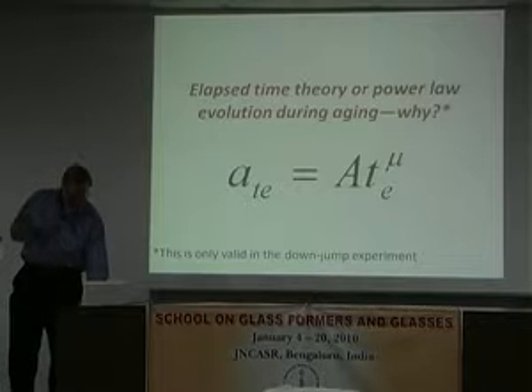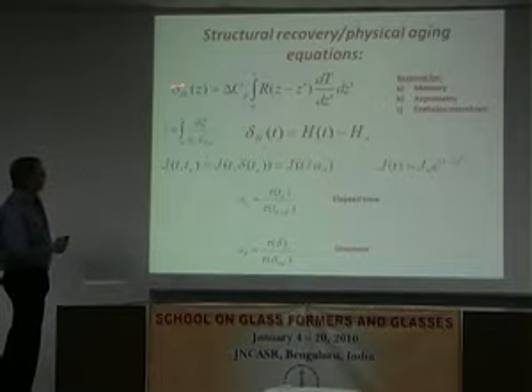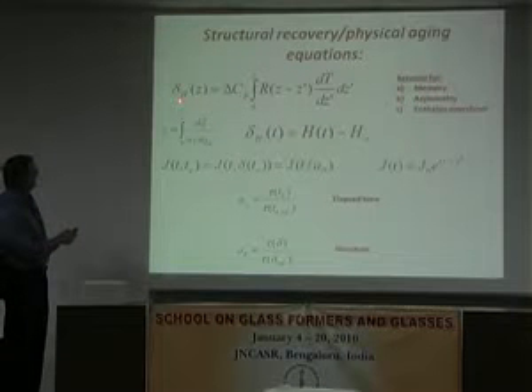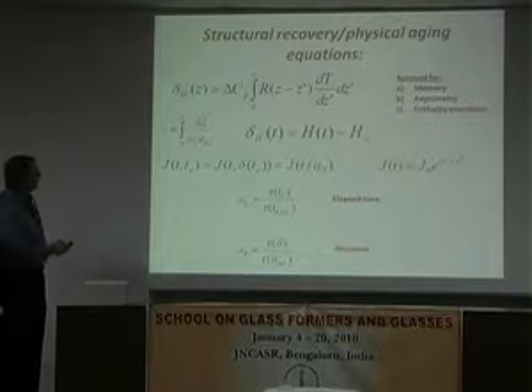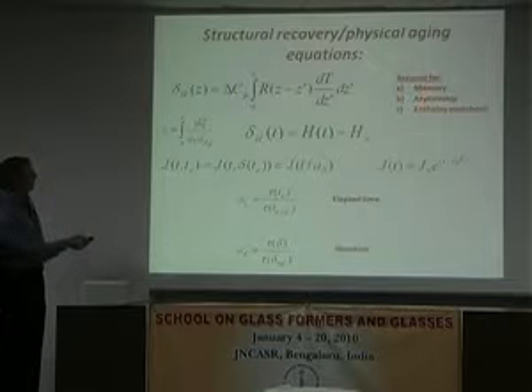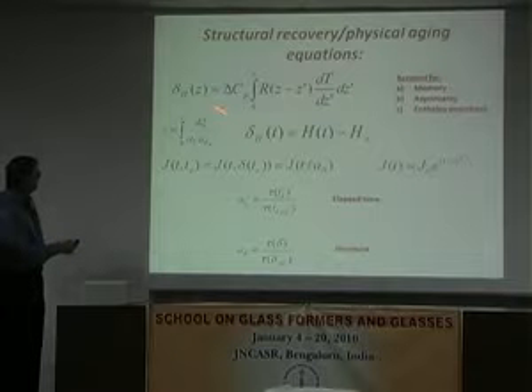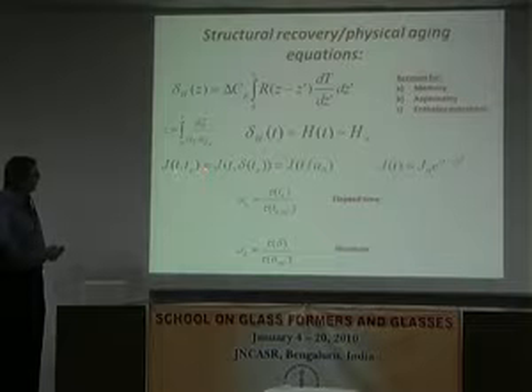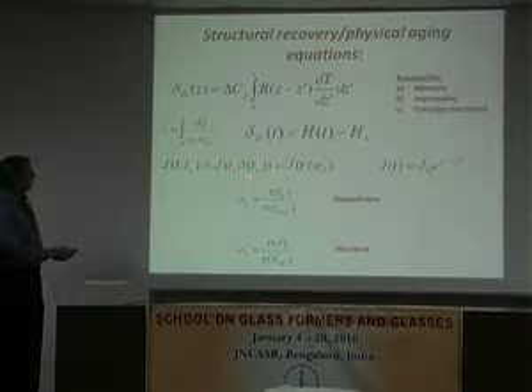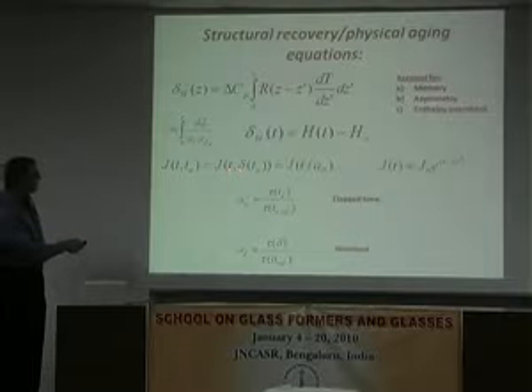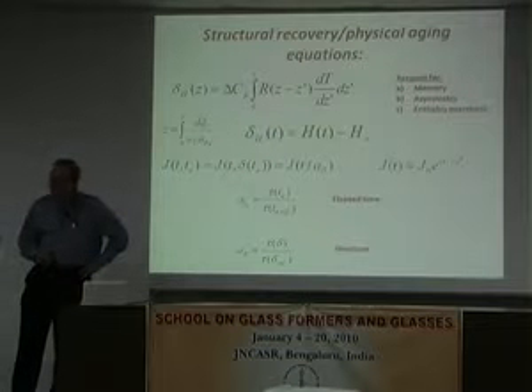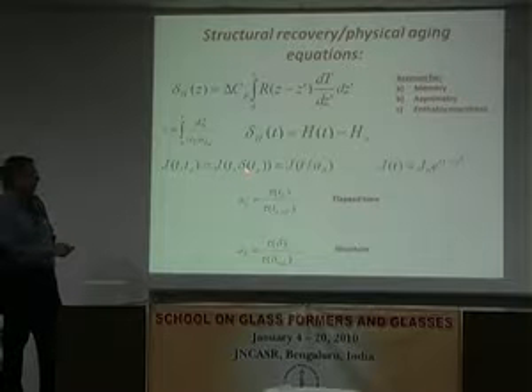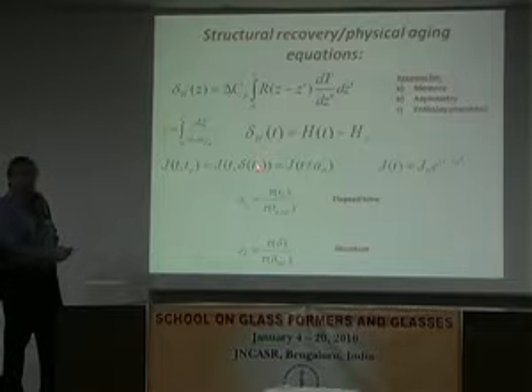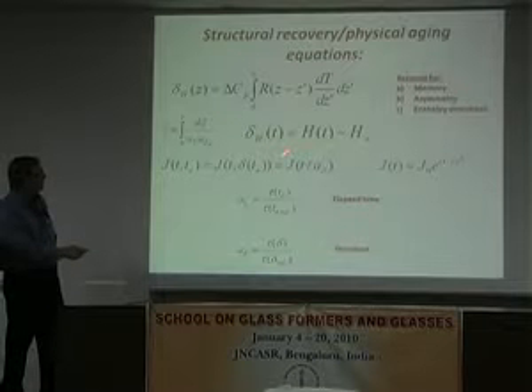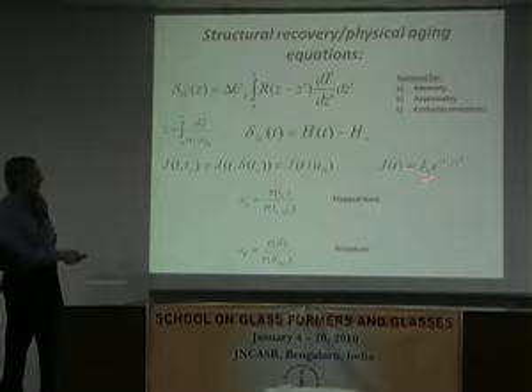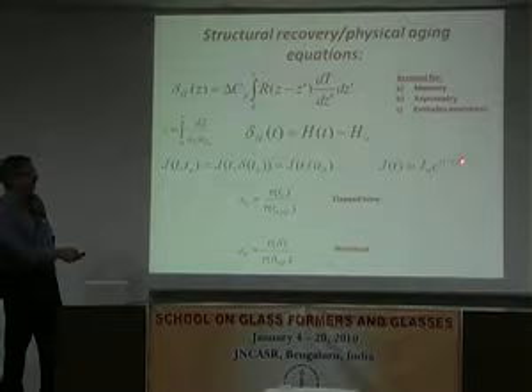But should you have a power law? That's the question. So, I wrote this down yesterday, actually for volume, but you can write it for enthalpy as well. And we know that it accounts for these kinds of behaviors. And this is my reduced time. And then if I want to write the creep compliance as a function of aging time, then in fact it should be a function of time and delta. It's a function of the structure of the glass. Or in this case, I put it as a departure, but I could put that as fictive temperature as well, which changes as a function of the aging time. And then you would write it like this. So it's a function of reduced time, where J is the creep compliance. And if you wrote it as a simple KWW function, it would look like that.